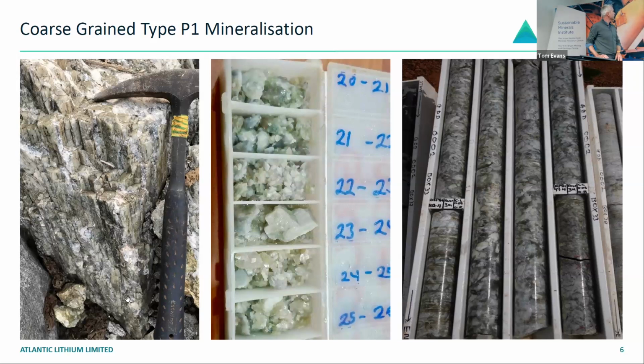But what's important is that 95% of our lithium occurs within spodumene, which are these green crystals here, and here in RC drill chips, and here in diamond core. It's very coarse grained. So the coarser the grain size and the more of your lithium credits that occur within spodumene, the better outcome you have from a processability point of view. It means you can more easily beneficiate and concentrate to a lithium concentrate or spodumene concentrate.